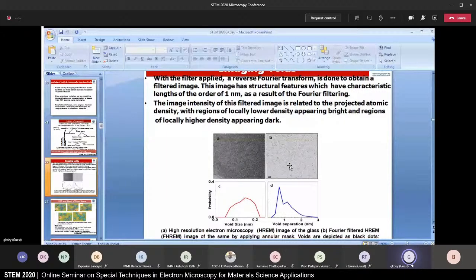So the third component in the structure has also been deciphered. You can measure the size of these voids. You can measure the inter-void distance as well. So just to conclude this part, these values are best interpreted by referring to the network where we have a void volume fraction, which is shown here.